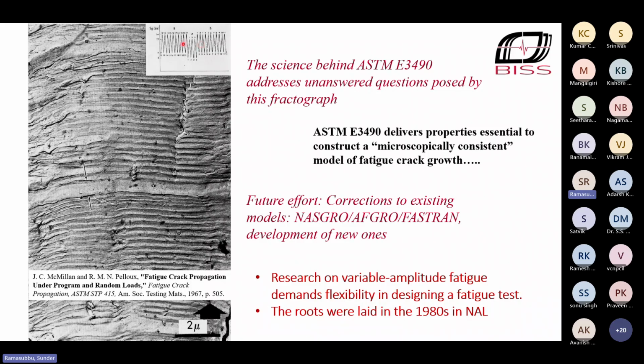This is the baseline cycling. The crack is growing from the bottom to the top. And then those 3 cycles, they're just growing at half the rate of the baseline, but they have the same range. And the change in stress ratio is very marginal. And these load levels are above crack opening load level, which is confirmed fractographically.